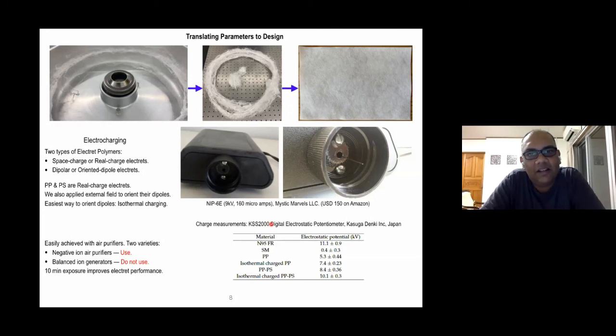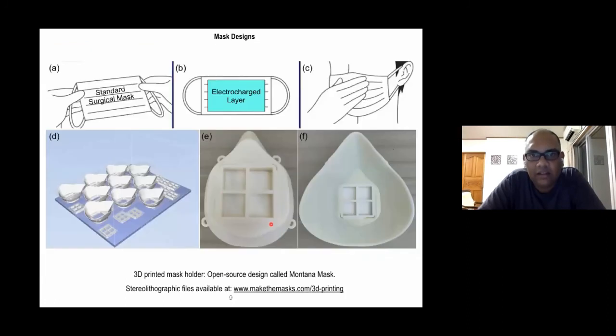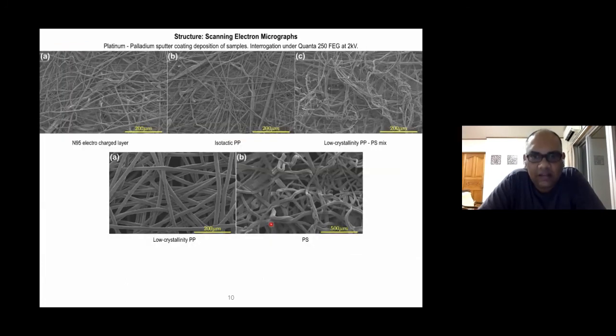Hi Mahesh, very cool. I'm glad I got to find out about your mask at last. My question was about the fiber scale structure of the mask. You showed us that the original N95 has these tortuous fibers, right? That tortuousness is probably good for smaller penetration. Is that correct? So why not just use only polystyrene? Why use a mixture with polypropylene? Because polystyrene is giving you a more tortuous fiber, right?